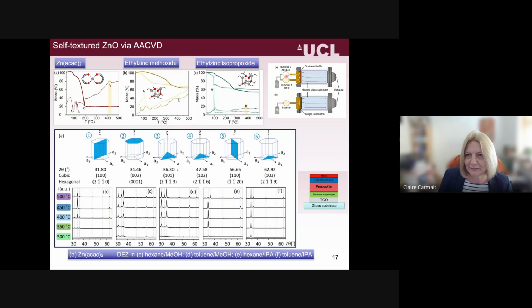Or what you can do is do a 2-bubbler setup. So you could have your diethyl zinc dissolved in probably toluene in one bubbler, and then your alcohol, so your methanol or your isopropanol, in the second bubbler, and then they enter into the AACVD, and as they react, they presumably form these types of species before forming the zinc oxide.